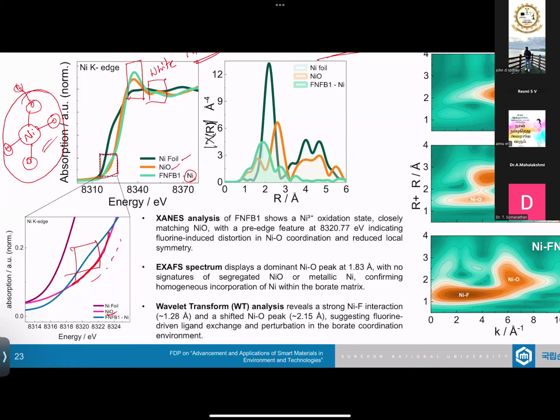In what way, we still have to prove it, but we confirm that this system is being altered slightly because of the inclusion of fluorine atom. So here also in EXAFS, we can see that the nickel atom confirms NiO bond. Further studies can be done with respect to bond angle and so on and so forth, which we haven't explored upon, but can be done. We are just much more focused upon nickel being altered.